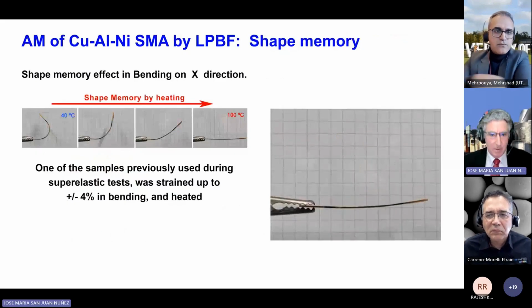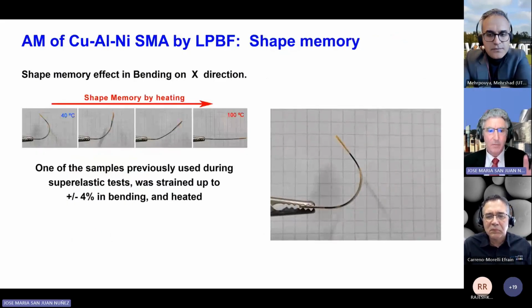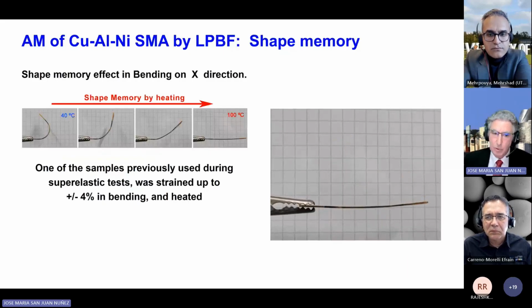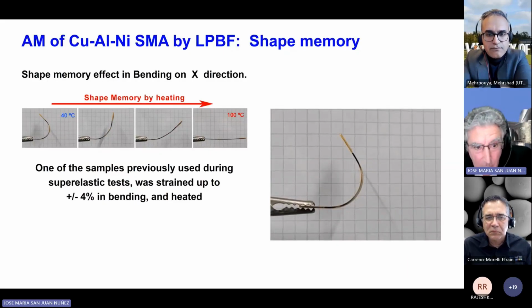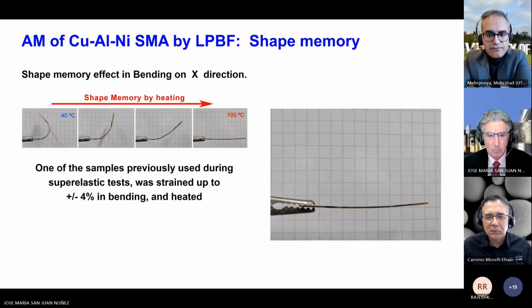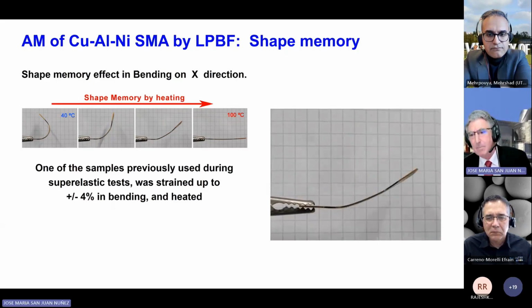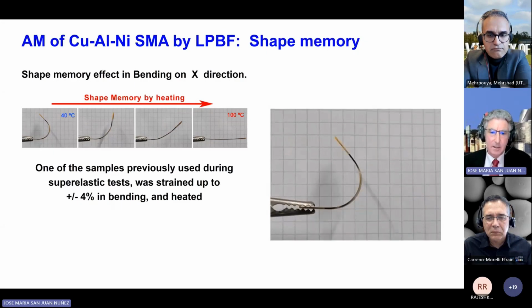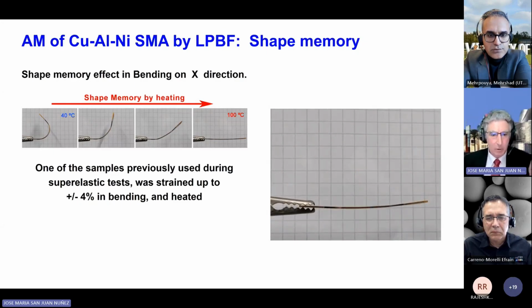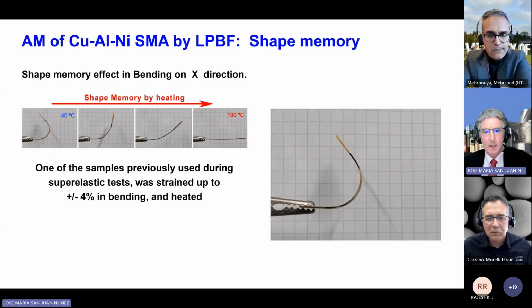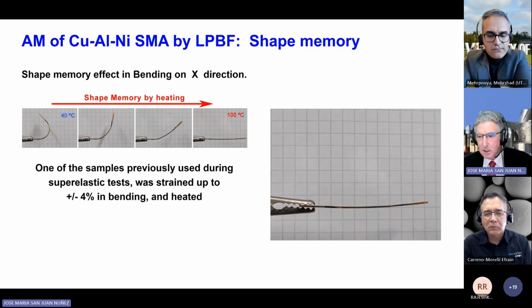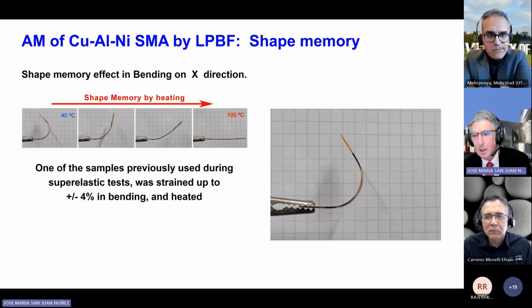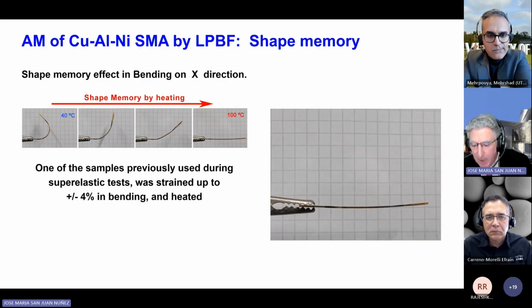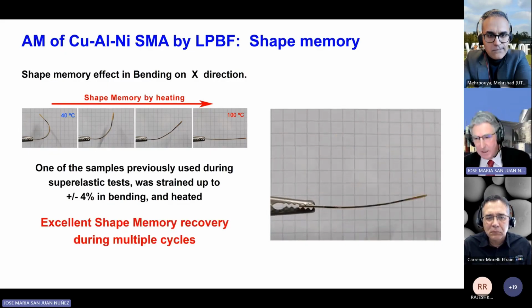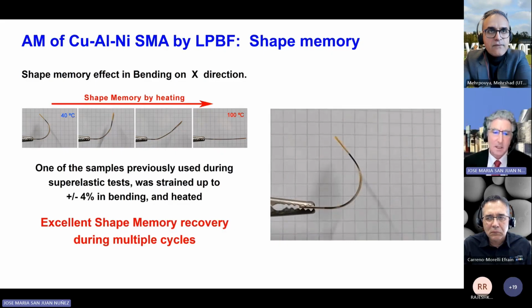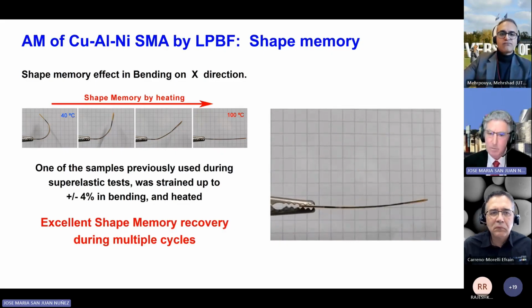So if we move to the behavior of shape memory, we have used one of the samples previously used during the superelastic test. You can see it's the same shape with the head for the tensile axis. But in order to visualize the shape memory, we strain it in bending plus minus 4%, and then heat it, and so you can see the easy way in which the material recovers the shape by shape memory effect. This has been done for many cycles, and the material exhibits an excellent shape memory recovery during multiple cycles.